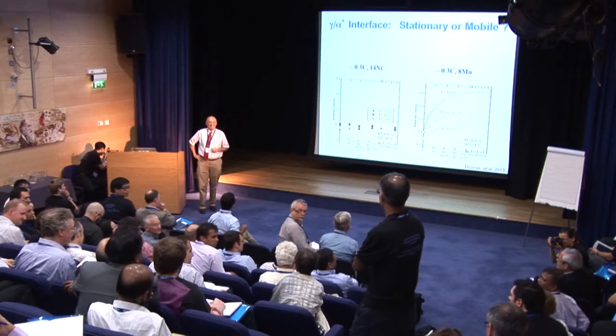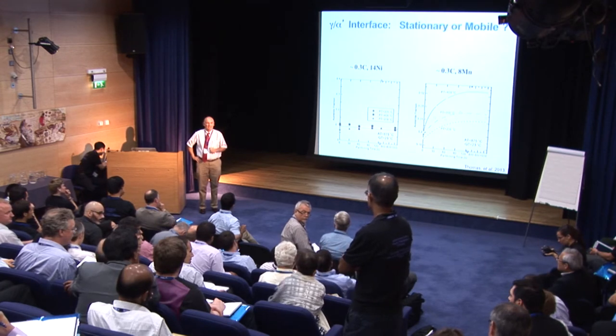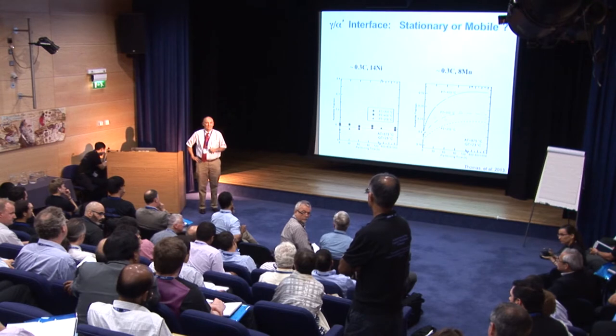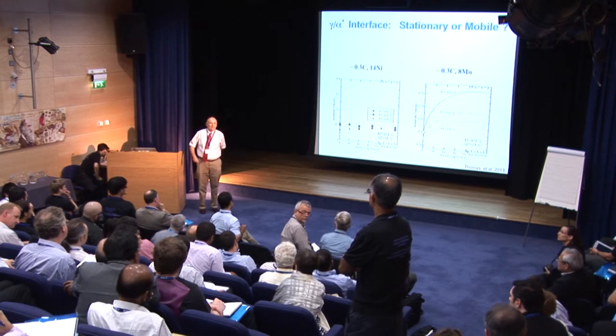John, I wonder if those unexplained experimental evidence that you saw may be related to carbon trapped in some places that you have not mentioned and should be considered, such as dislocations, twins, or other interfaces, because quenching the steel before that isothermal aging, you create high dislocation densities. And I wonder if the carbon will be really comfortable on those spaces before partitioning to the austenite. Then maybe you are losing carbon in the process of carbon partitioning, which cannot rule out the carbon balance that you are considering for the way of retaining your austenite at room temperature at the end.